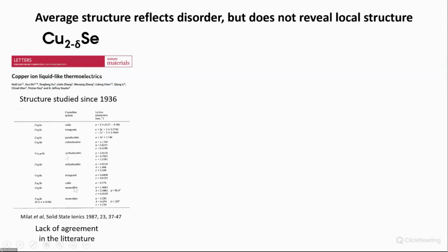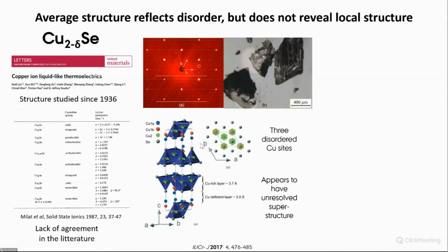If you're diplomatic, you just say there's a lack of agreement. But in all crystallography, it's about crystals, and a lot of our activities are centered on synthesis. In this case, we were able to do a gas transport synthesis and get quite decent crystals, and then measure some nice Bragg diffraction data. From the Bragg diffraction, we could refine the average structure, and it's highly disordered on the different copper sites.